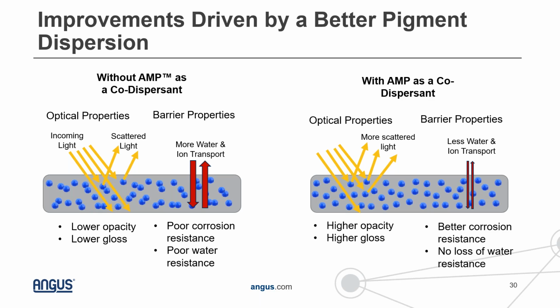In the case of when we're using AMP as a co-dispersant, we believe we're getting a much better distribution of our pigments into that coating formulation. And so we're getting better opacity, better gloss, and this is coming through more scattered light because your pigments are better dispersed. This can also affect your barrier properties. So we're seeing improvements to corrosion resistance, and we're not seeing any loss to our water resistance, especially our early water resistance. So a lot of these properties can really be tied back to the quality of that dispersion.